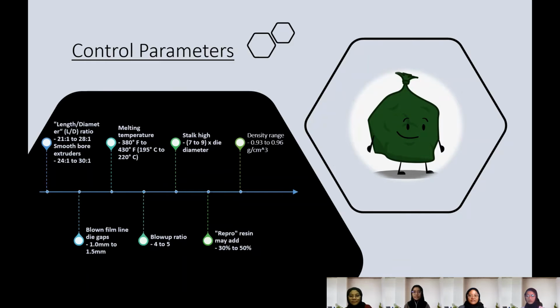Okay, thank you, Karina. So the control parameters for blown film extrusion: the ratio of the length to diameter is 21 to 1 to 28 to 1. The smooth bore extruders is 24 to 1 to 30 to 1. The blown film line die gap is approximately 1 millimeter to 1.5 millimeter. The melting temperature is about 380 Fahrenheit to 430 Fahrenheit, which is equivalent to 195 degrees Celsius to 220 degrees Celsius. The blowup ratio is 4 to 5. The stalk height is approximately 7 to 9 multiplied with die diameter. The regrind resin that may be added is approximately 30% to 50%, and the density range is about 0.93 to 0.96 gram per centimeter cube.